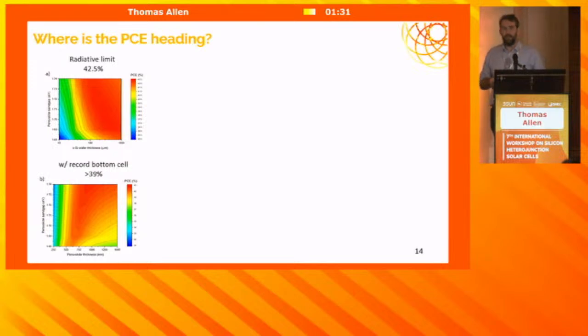Okay, so where is the efficiency heading? So the radiative limit here is calculated. You have a kind of broad optimum around 42.5%. That's not including radiative coupling, which tends to give an even broader optimum and a slightly lower efficiency.